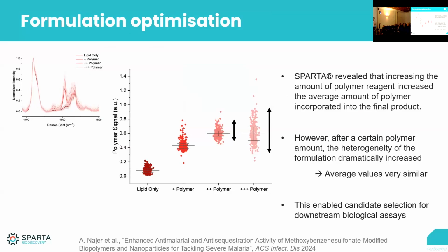Crucially, what they've used it for is then to optimize their formulation. So they go through different steps and see how much polymer they could actually add to make this formulation effective, because the polymer was really the part here that can interact, through a charge-based interaction, with this parasite. So they wanted quite a lot of that polymer.